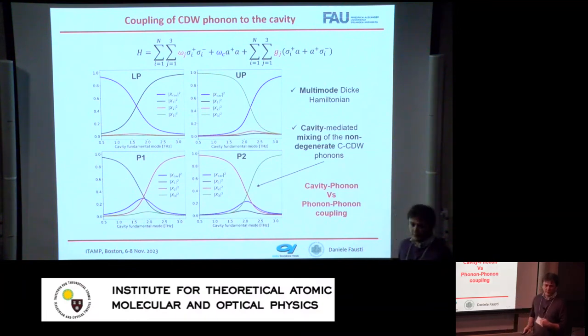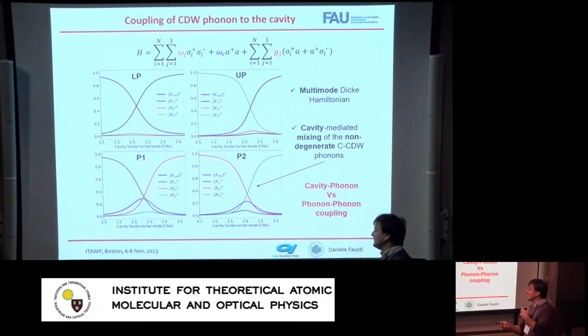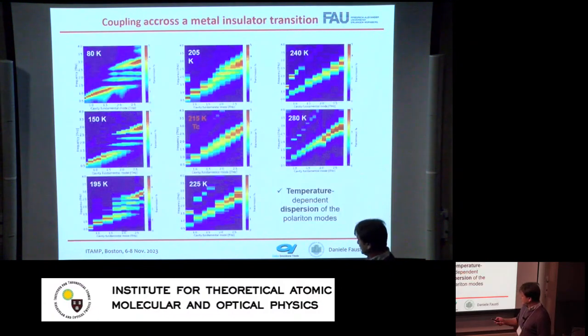Sorry, what's on the vertical axis? The vertical axis is the modulus of the component of the wave function. So essentially, this is telling me for the four states I observe how the wave function is composed. For the lower polariton and upper polariton, I switch from being mostly cavity mode to mostly one phonon mode where the cavity goes across, and the same for the upper polariton. But the two states in between are composed by two different phonon modes and the cavity mode. So I can expect that the nonlinearity here could be relevant in the sense that I mix different phonon modes.